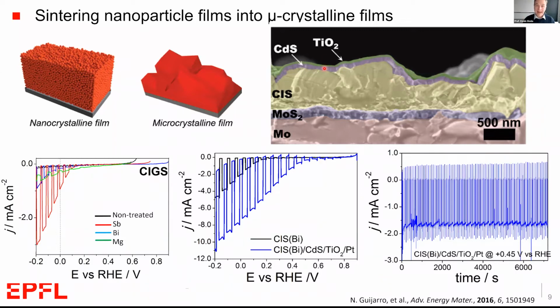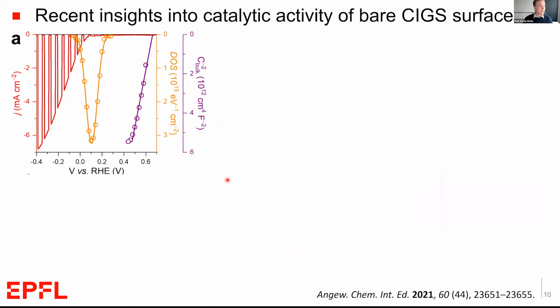More recently, we've been quite interested in this system because we noted that even without any overlayers, without the cadmium sulfide, without the titanium dioxide, and even without the platinum, as shown in this black curve here, we can achieve some promising photocurrent. And the idea of using this material in a photocatalyst or in a very simple photoelectrode system without any overlayers, just directly using the material, is quite interesting, especially from an economic aspect. So our more recent studies have been focusing on understanding what's going on at the surface of this CIGS material.